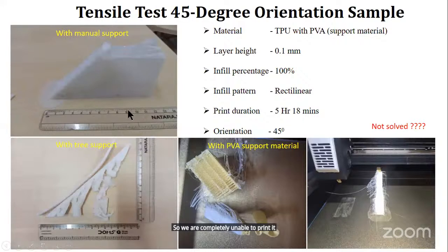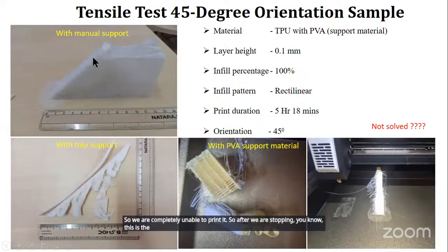After we stopped, this is the support structure and this is the actual component at 45 degree. You can see this is the support structure and this is the tensile sample. So this is the 45 degree. Stringing and all those errors are coming, but still we are unable to solve this problem for the TPU material.